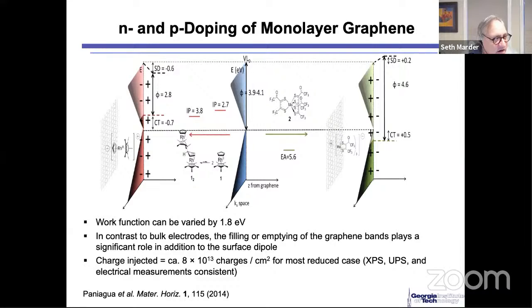In the case of the electrodes that I referred to before, the change in the work function is basically solely defined by a shift in the vacuum level. In these systems, the change in the work function is not only defined by that, because you only have a monolayer of the material. If you start doping, you start actually filling the Dirac cone that is unoccupied. So you're actually doing two things. One is you're filling the empty conduction band, it's now not empty, and you're shifting the vacuum level.